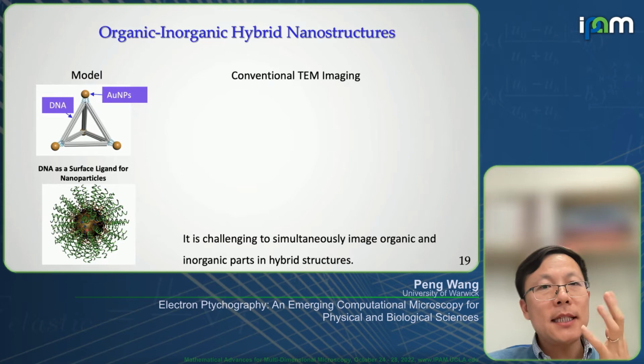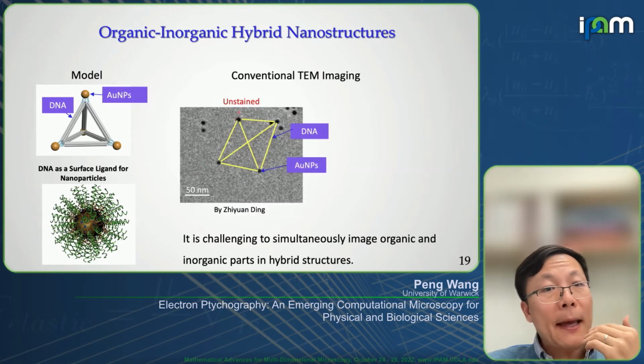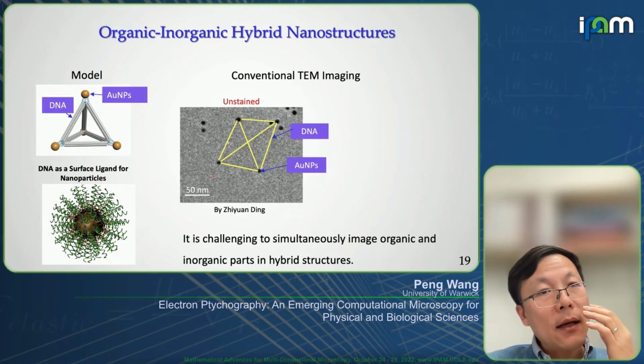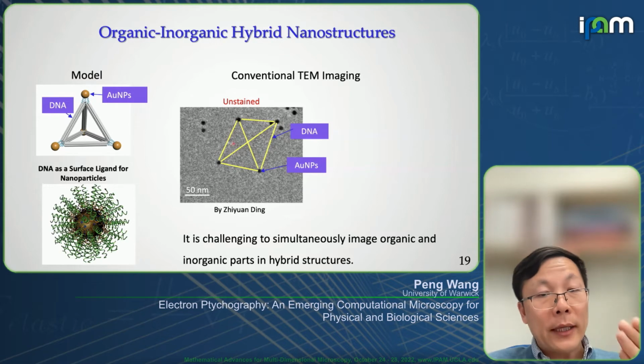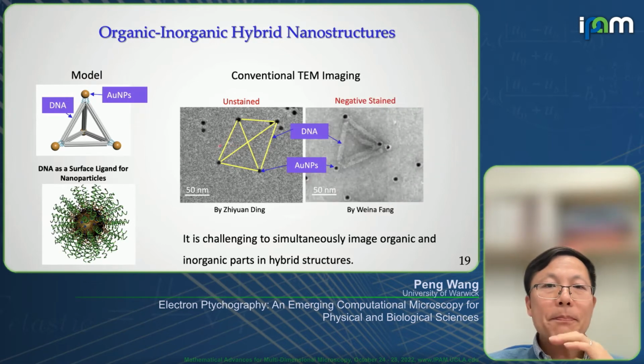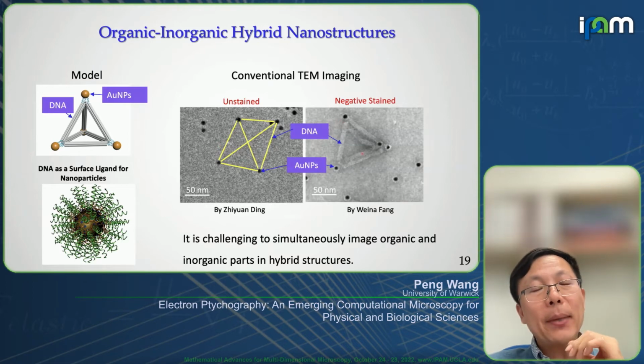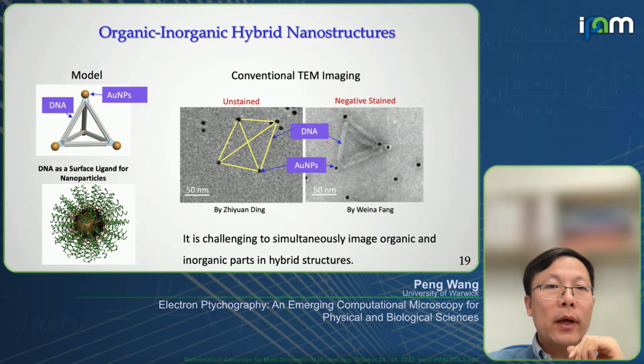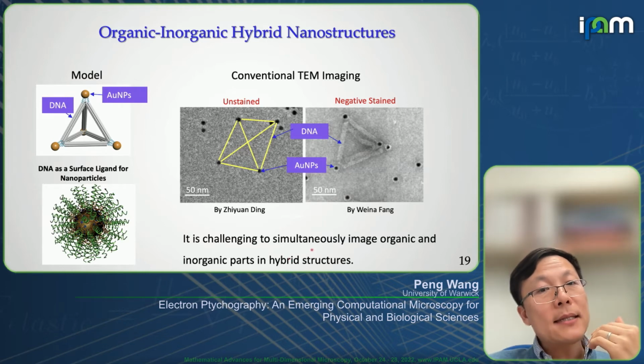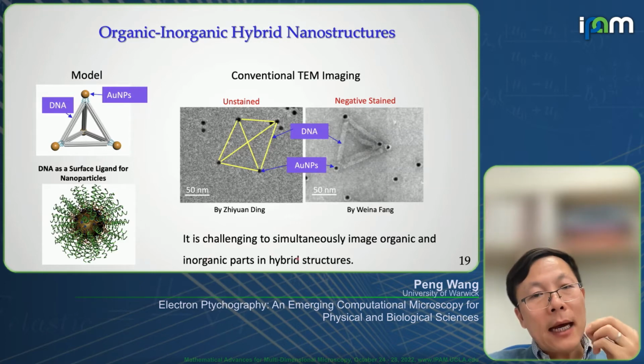In conventional TEM, as you can see, if the DNA is not stained, by using conventional TEM imaging you only see those gold atoms. However, the contrast of DNA is really low against the background of this carbon support. What people always do is use a negative stain, but as you know, when you do negative staining, sometimes you alter the structure and do not see the real structure of the biomaterials. That's why it's challenging to simultaneously image organic and inorganic components in this type of hybrid nanostructure.